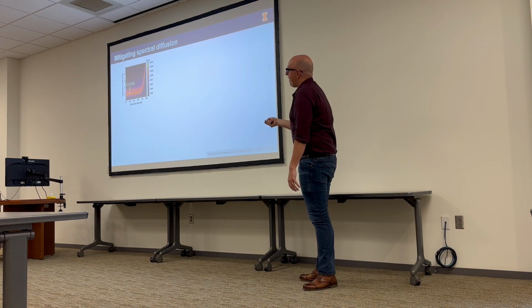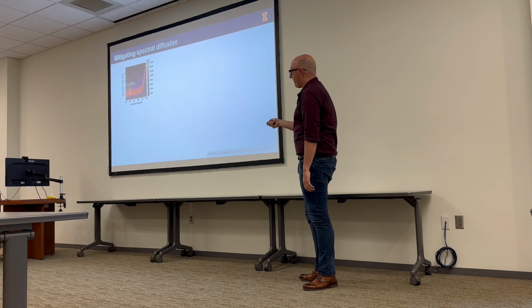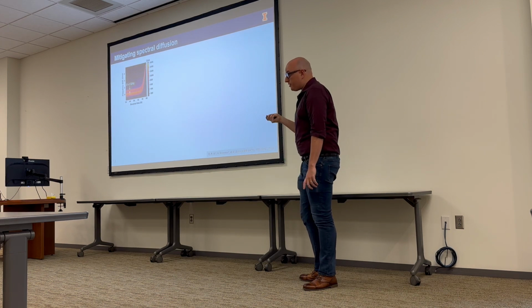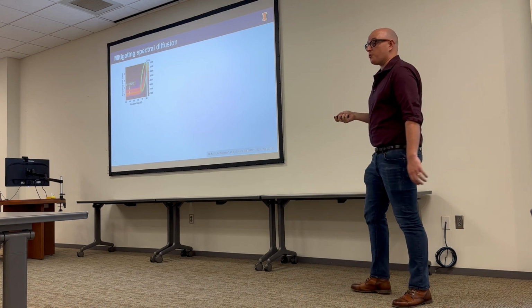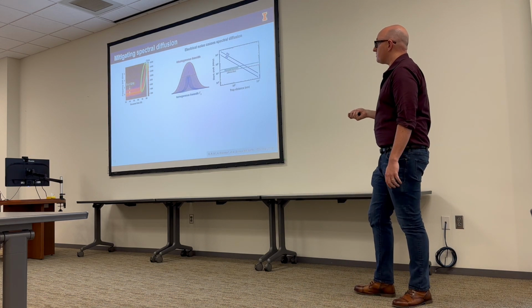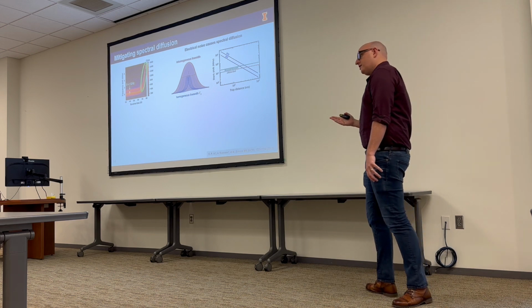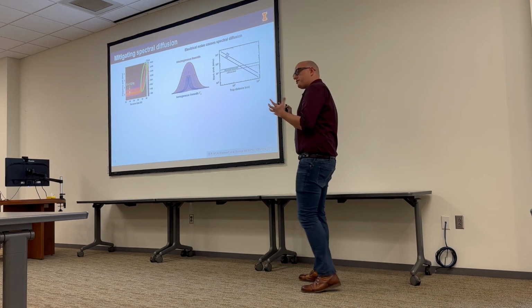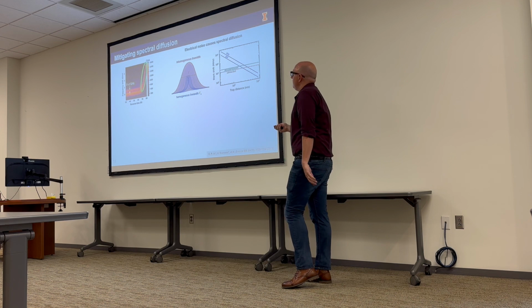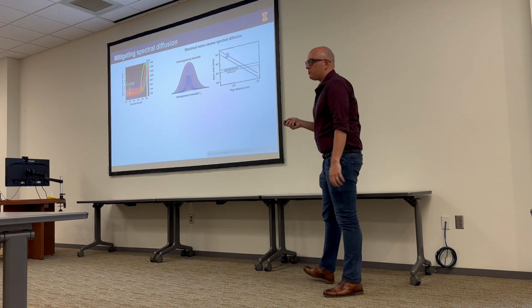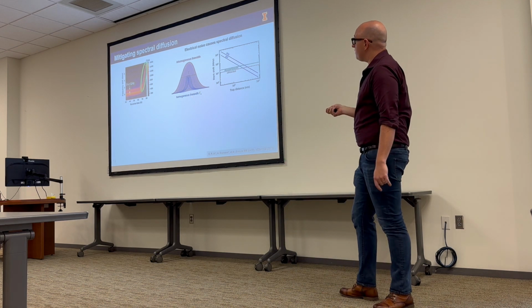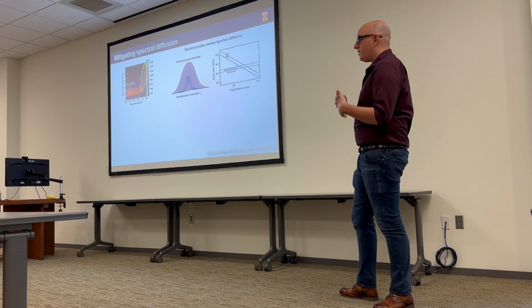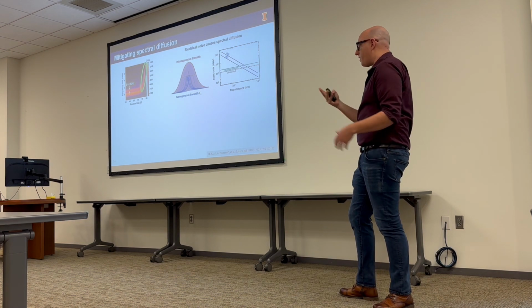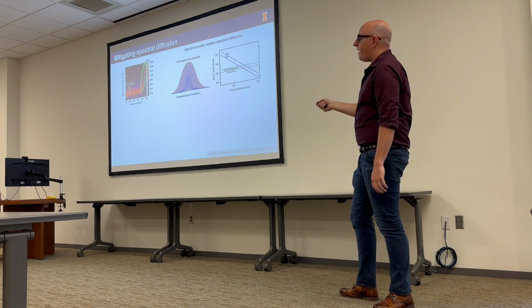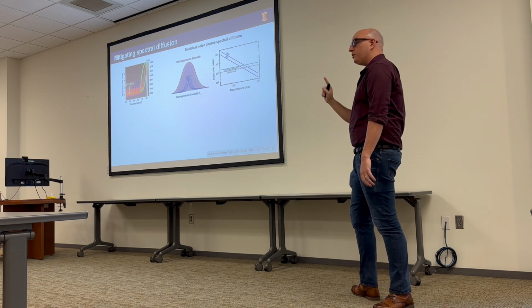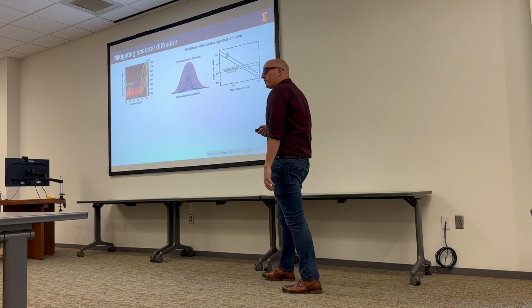So we have this optical emission, we're applying voltage, at first nothing happens, but around 70 volts it starts to shift, but it's not just shifting, it's also narrowing. And that's really exciting because I told you that each of these defects feels local strain and local electric fields, and I can shift them with electric fields. And actually, solids are just horrible places for single photon emitters to live because they're sensitive to stray fields, and solids are just noise. There's free electrons and holes everywhere. They're fluctuating around. And so our line basically jitters around because of this local electrical noise. We call this inhomogeneous broadening.